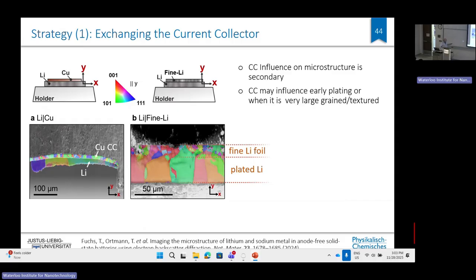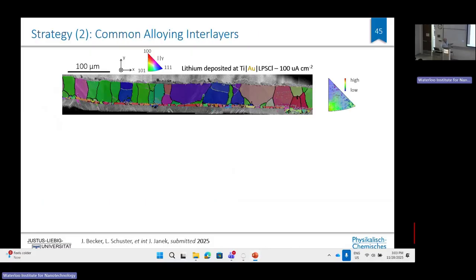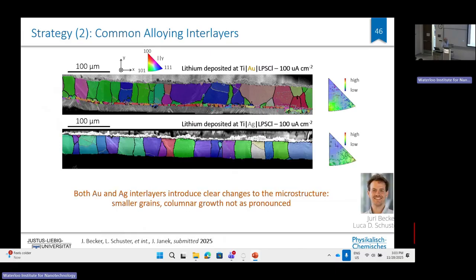And so what you see is the copper current collector is, of course, quite small grain, and the grains grew much, much bigger. So first of all, the current collector we found has no influence on the grain size. So the idea to use a current collector that is somehow defining grain size of the lithium, that doesn't work. But if you then take, for example, gold as an interlayer, or silver as an interlayer, this is on titanium current collector, then in principle we see there is an effect. Grains remain smaller. I would say it's not super impressive, but you can somehow control the grain size already. So I would say this is a good starting point.